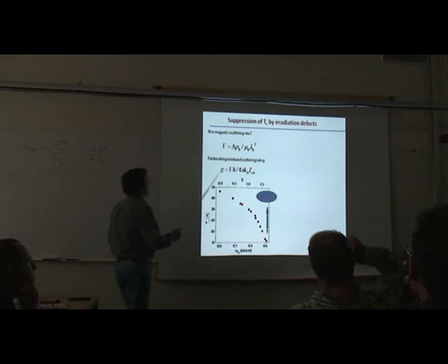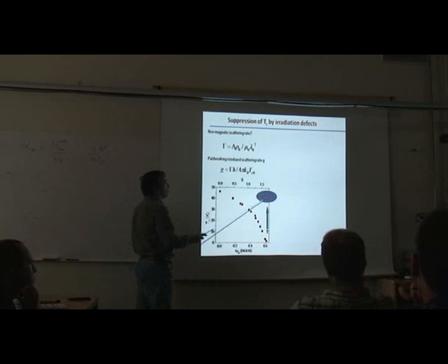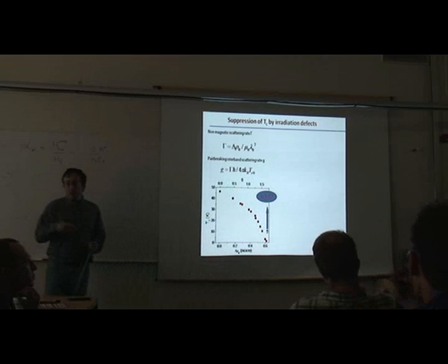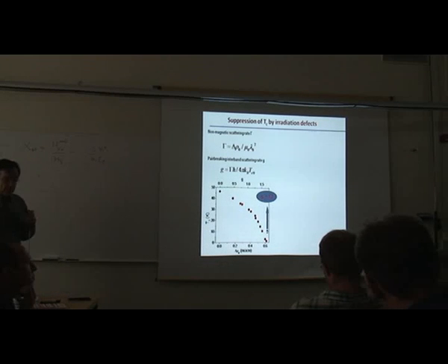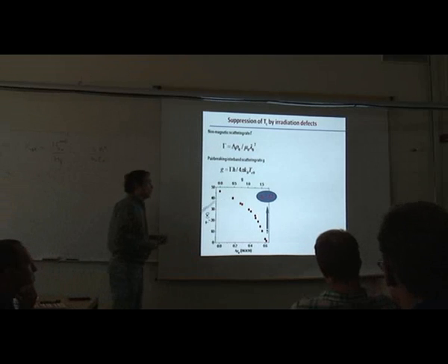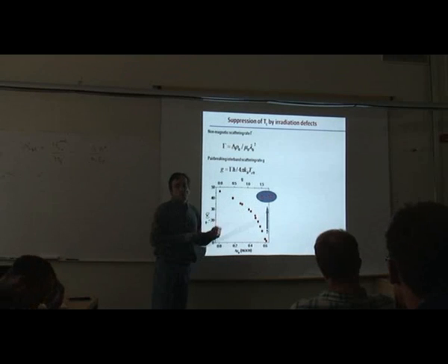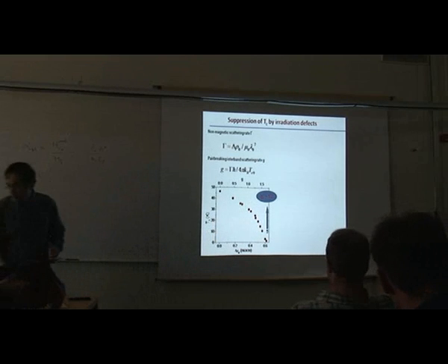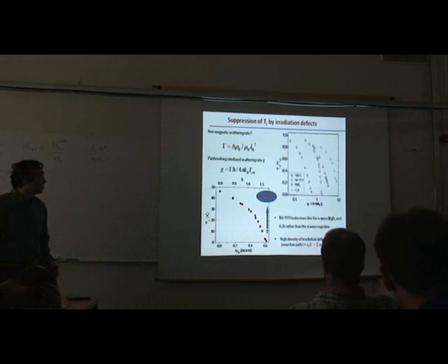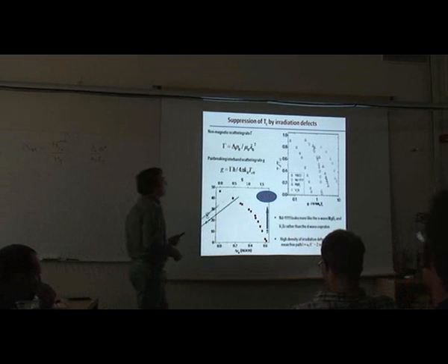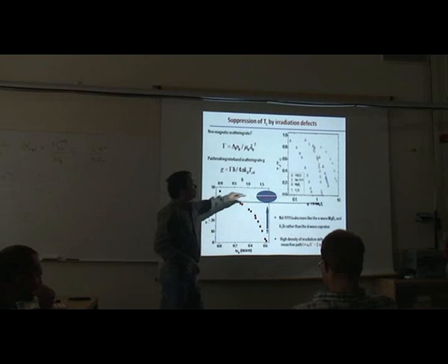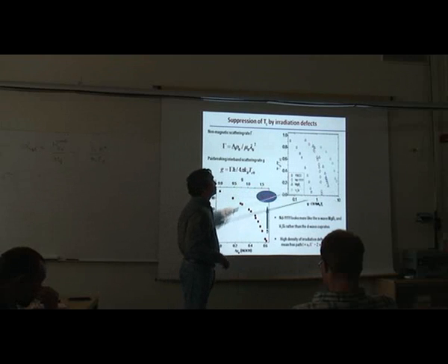And we can calculate the critical value of this parameter at which Tc goes to 0. It's 1.7. As I said before, magnetic pair breaking is very strong, and in conventional Abrikosov-Gorkov type theory, this critical value should be 10 times smaller. It's 0.17, if you treat scattering in the Born approximation. Then what we did, we used the same analysis to compare different materials here.